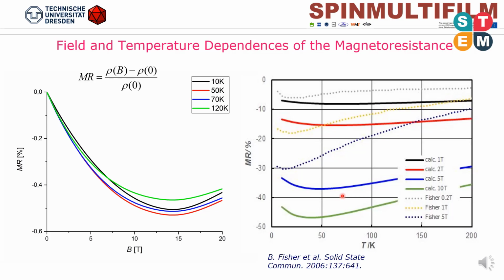The increase of the absolute values up to a temperature of 50 Kelvin, followed by a further decrease, is in accordance with experimental data for granular strontium ferromolybdate samples which were related to the fluctuation-induced tunneling model. The calculation confirms that contrary to manganite and strontium ferromolybdate ceramics, the magnetoresistance of nano-sized strontium ferromolybdate, strontium molybdate core shell structures is only weakly temperature dependent. This would be an advantage for device application near room temperature. The calculations are in qualitative agreement with experimental results of sintered granular strontium ferromolybdate obeying the fluctuation-induced tunneling model.